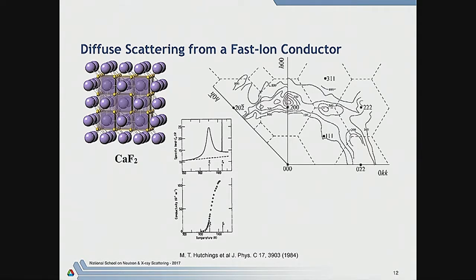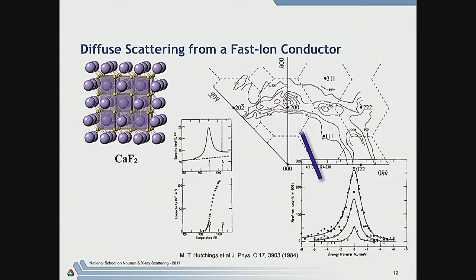And diffuse scattering turned out to be a very powerful way, here again measured on triple axis, of modeling that disorder. So here we see a peak beyond the 200, which only builds up in intensity. This is a function of temperature. So this is low temperature going up to very high temperature. And as we go through this superionic transition, you get a big buildup of intensity in this diffuse scattering.